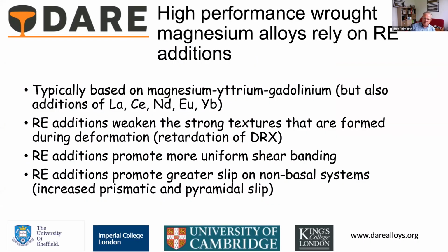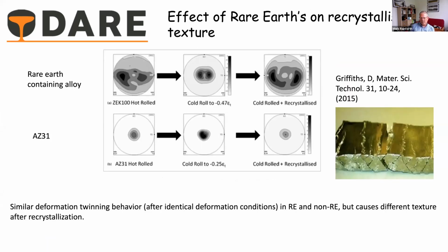So the wrought alloys tend to use these rare earths, typically magnesium with yttrium and gadolinium, as an example. And it all comes down to the crystallographic texture. If you have a standard magnesium alloy, then it has a very strong crystallographic texture, where the basal planes become all aligned, and you can see that in the bottom series there, where it shows a very strong texture of the basal pointing vertically upwards.